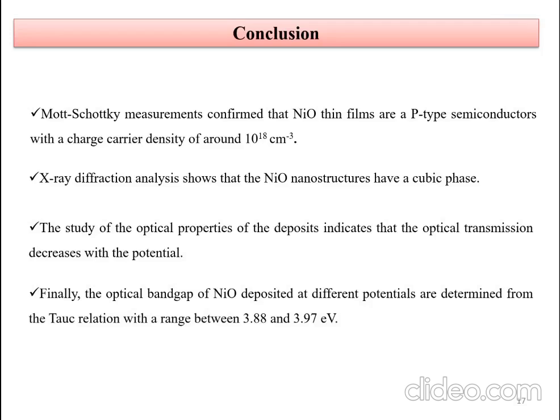Finally, the optical band gap of nickel oxide deposited at different potentials was determined from the Tauc relation, with a range between 3.88 and 3.97 electron volts.